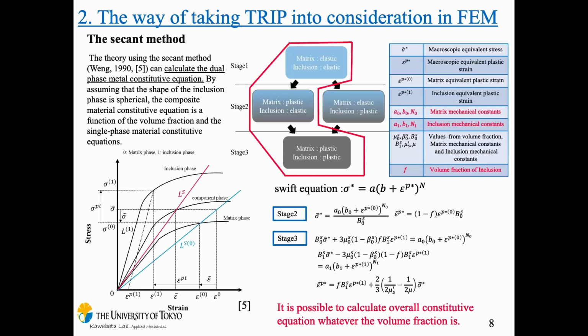The secant method is the way to calculate the dual phase metal constitutive equation from the single phase constitutive equations and the volume fraction. And there are two phases, called inclusion and matrix. And in the uniaxial tensile test, the deformation is divided into three stages. In stage one, both are elastic. In stage two, one of them is elastic, and the other is plastic. In stage three, both are plastic. And in all stages, we can get the overall stress and strain using these secant equations. And so it is possible to calculate the overall constitutive equation, whatever the volume fraction is.